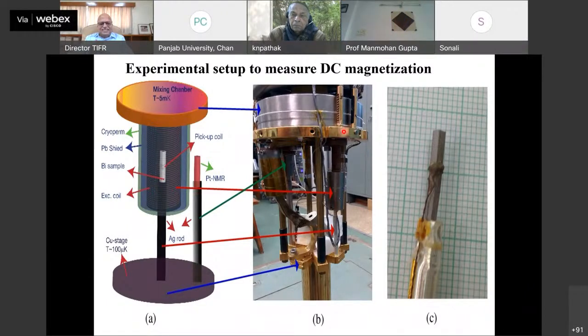And what you see here is the nuclear stage, which is at the bottom, and the magnetometer, everything is coupled to the mixing chamber, and the sample is attached to this nuclear stage, and the pickup coil comes to the SQUID, which is mounted upstairs in this system. And what you see here is a silver rod, which is shown here in the third photo, and the bismuth crystal, which you see here, is a very long crystal, because the connection to the silver should not affect the superconducting properties of bismuth, so the coil is kept far away from there.